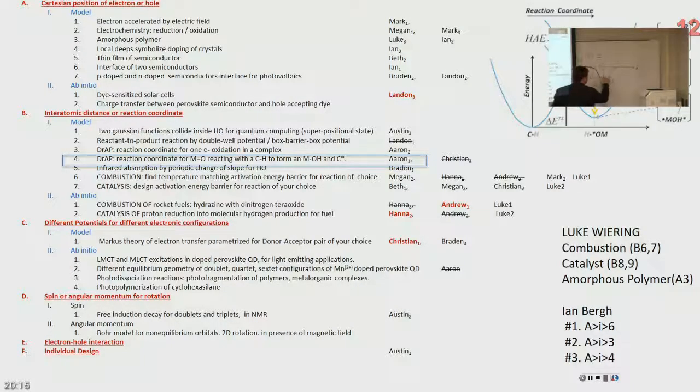and we need the width of this shape, which will be like ionic radius that you can pick in tables, periodic tables from internet, or just guess. If there is a crystal lattice with tightly packed atoms, the width cannot be bigger than interatomic distance. It should be some number like half of the interatomic distance for the first approximation, if you have no data and no guess. Okay?